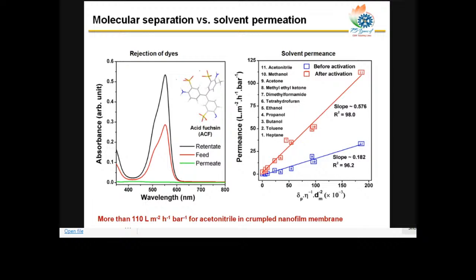So using this polyamide membrane, we can separate a model molecule like acid fuchsin very fast, because the solvent permeance was 110, and compared to the commercial membrane it is more than two orders of magnitude higher. The solvent permeance on the right follows a three-parameter dependency, not like the previous case, the carbon nanosheet, where the solvent permeance depended only on its viscosity. However, in this case, we found it also depends on the polarity of the solvent. Obviously, it also depends on the viscosity and the molecular diameter of the molecule.